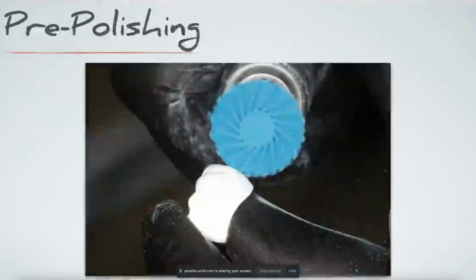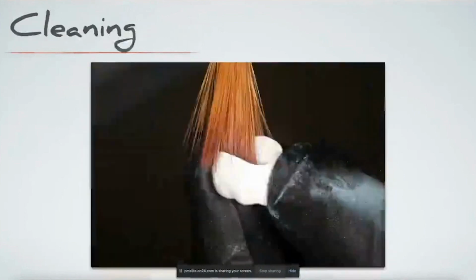And once this is polished off, we use these blue wheels from Meisinger on a relatively low speed. And this is what's taking off those surface scratches that you saw, right? And I'm going to do this either way. If I don't polish away those scratches now, they're going to be much more difficult to polish away once it's been sintered. Once zirconia is hard and sintered, adjusting it is not as easy. Pre-polishing it now when it's in this soft green state, as we'll refer to it, then it's an easier transition to get rid of the lumps and bumps that may be left behind from milling, and to define that anatomy a little bit more.